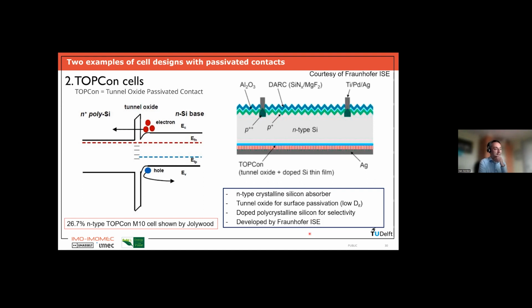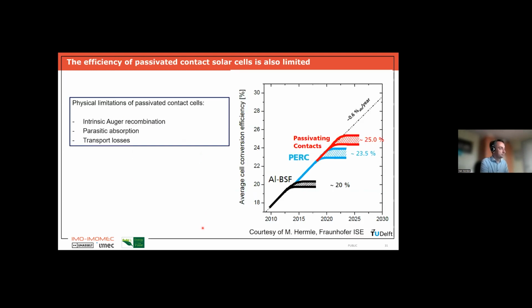And at the moment, the highest cell efficiency achieved for this type of cell is 26.7%. So it's very close to the 26.8 we saw. And this was also achieved on large wafers and achieved by a Chinese company, in this case, Jolywood. So you see, the heterojunction and the TOPCon cell, they both lead to efficiencies almost of 27%, but these are, of course, the champion cells from the lab.